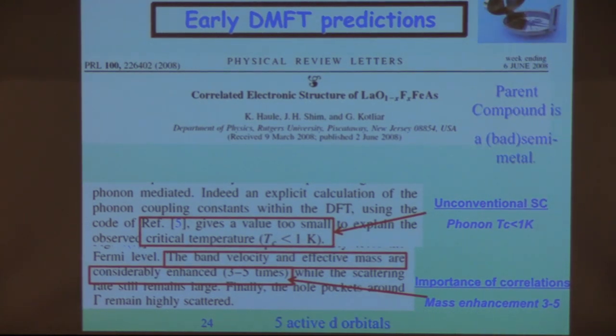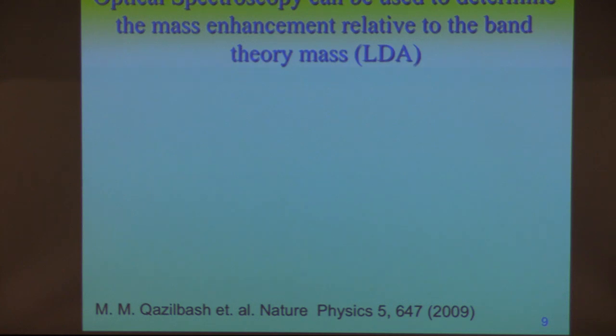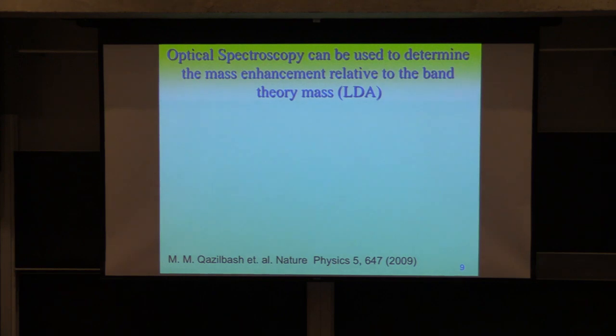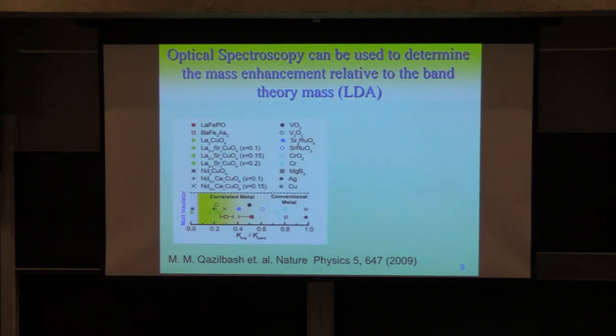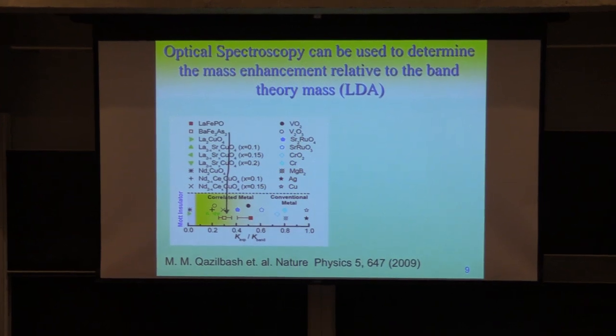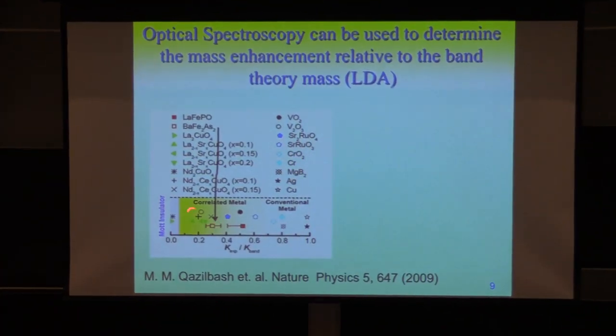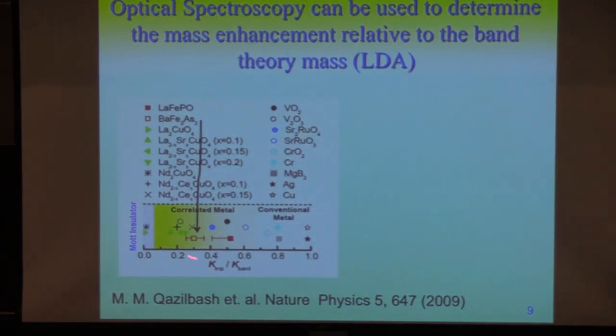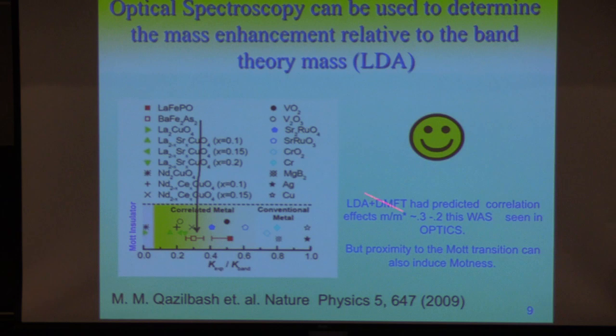So that's our prediction. That was done in 2008, and there were a lot of arguments in the community. This is a very contentious community, about whether this is correlated or not, etc. But eventually experiments come in, and one year later, there were sufficiently good optical measurements. The m*/m of this compound, the 1/m* was measured, and it was around 1/3. So that's what we had said, a mass enhancement between 3 to 5. So in that sense, these calculations were already telling us that we're on the right track. So that was one type of prediction.